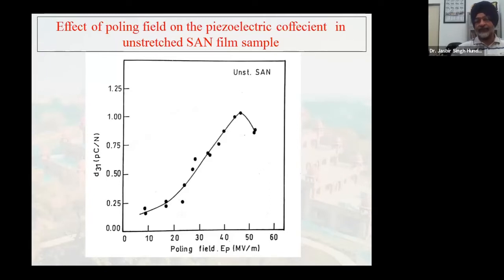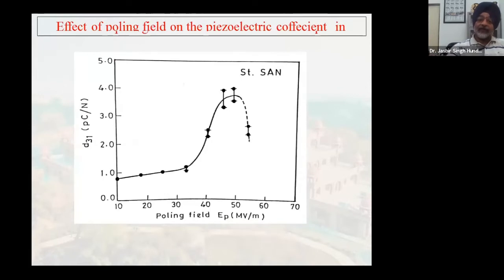Because of the increase in polarization, despite the fact that it is an unstretched film, we still find that D31 increases and becomes maximum at 45 MV per meter, and beyond that there was electric breakdown in the film and D31 decreased. Now look here, this is for stretched styrene acrylonitrile film.